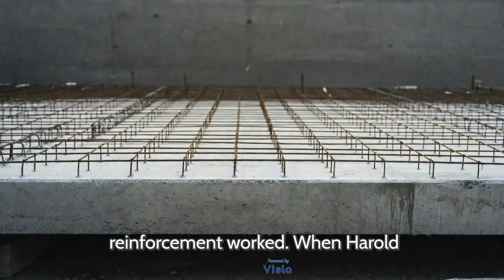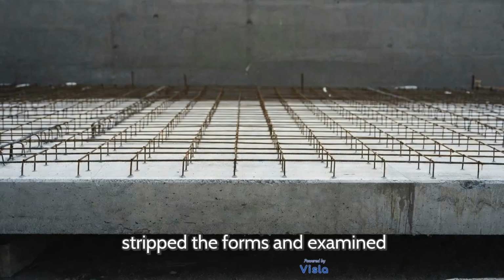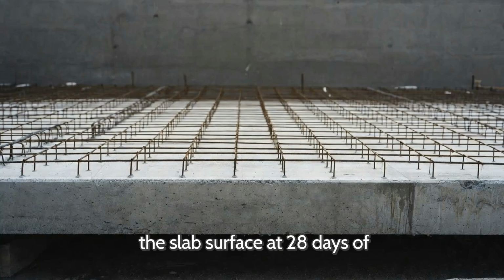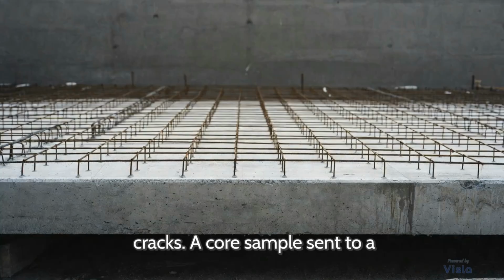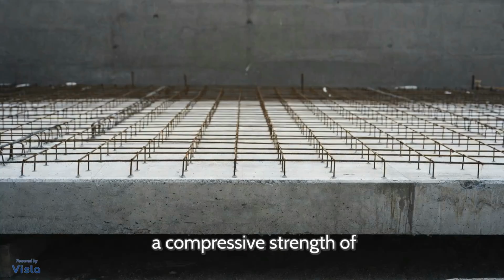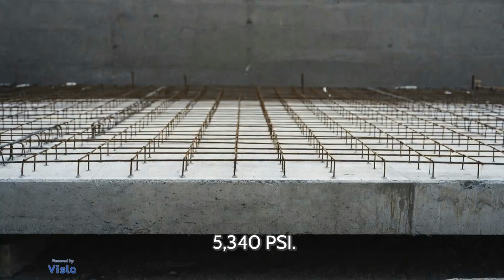The fiber reinforcement worked. When Harold stripped the forms and examined the slab surface at 28 days of cure, the standard test age for concrete compressive strength, there were no visible shrinkage cracks. A core sample sent to a laboratory in Anchorage returned a compressive strength of 5,340 psi.